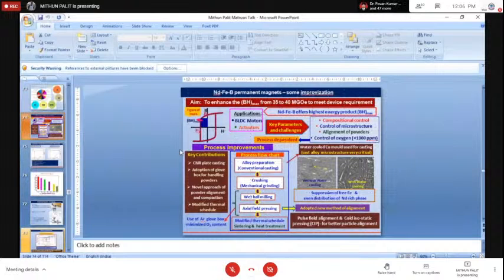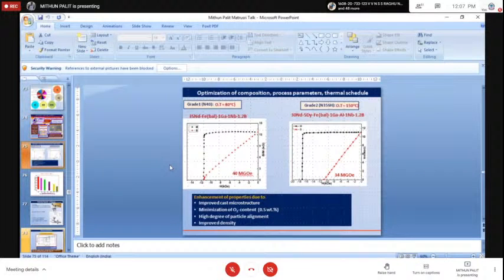But in the neodymium iron boron magnet, what was observed is that if the starting material has a desirable microstructure, with the rare earth rich phases circling around the 2-14-B phase, then it is probably beneficial. Accordingly, a method called strip casting is used, where an extremely high cooling rate is used to quench or solidify the material to get the nice microstructure as shown in this slide.